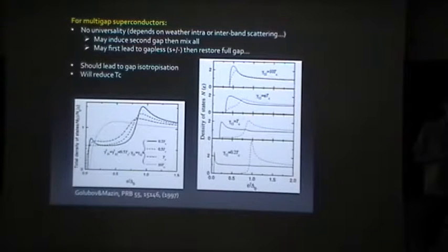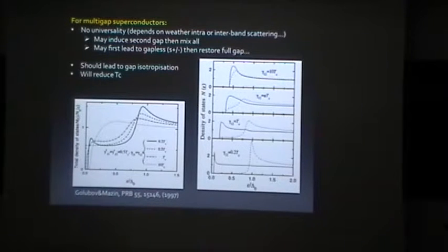Due to this interband coupling, you induce superconductivity in the second gap. And of course, in any spectroscopy, you can see both gaps. For instance, in Raman, you directly measure both gaps, so you don't need to do that. If you can see the collective mode, this is probably what is experimentally most directly related to the interband coupling. This is a phase mode between the two order parameters, driven by the strength of the coupling between them.